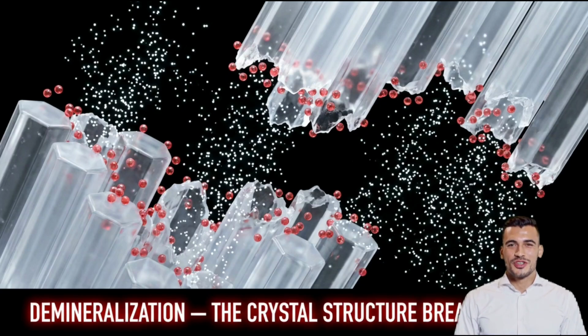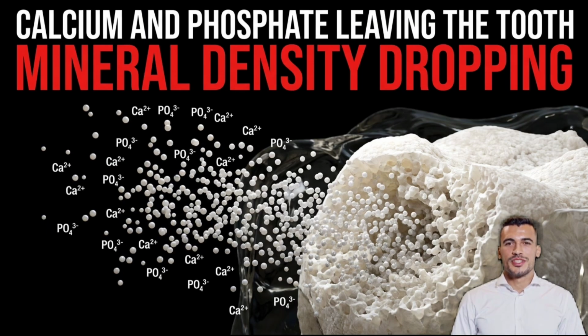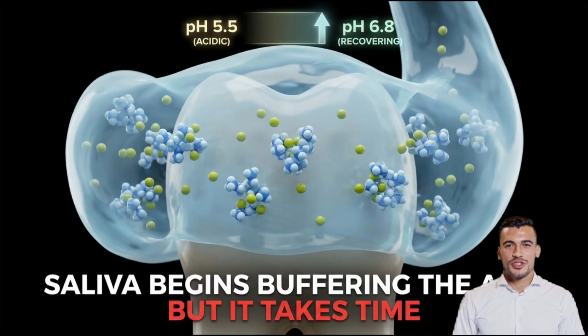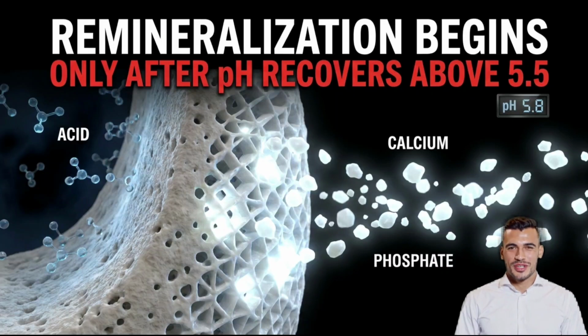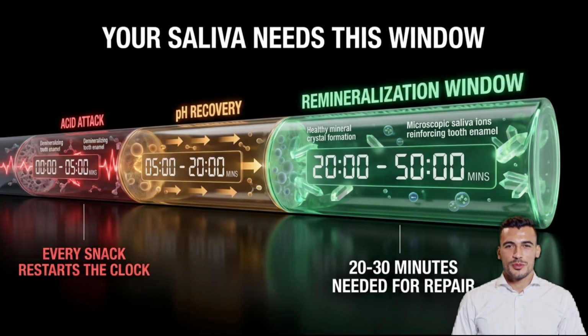And here is the mechanism that makes it so destructive. When fermentable carbohydrates enter the mouth, sugars, refined starches, anything that breaks down into simple glucose or fructose, Streptococcus mutans metabolizes them through glycolysis and produces lactic acid as a byproduct. Within minutes of sugar contact, the pH at the tooth surface drops. Normal oral pH is approximately 7, neutral. Below pH 5.5, hydroxyapatite begins to dissolve.